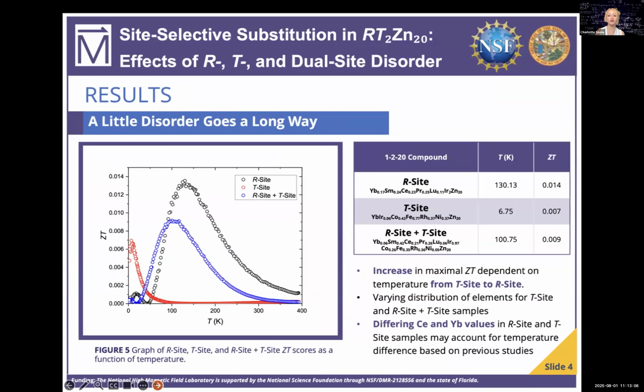There was actually a large difference in what temperature yielded the best ZT score between the R and T site samples. Specifically, the T site sample did better at lower temperatures, while the R site sample did better at higher temperatures. And this temperature-dependent behavior is likely influenced by elements like cerium and ytterbium, whose electrical properties, as we've seen in past studies, change in distinct ways as temperature varies.